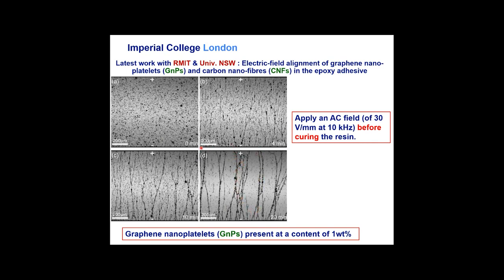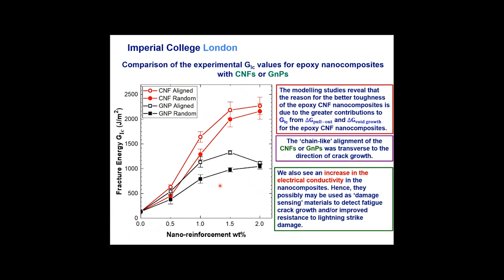And bear in mind, of course, there's one CFRP substrate there, another one there, and the crack will try to travel down through the adhesive. And therefore, these chains of GNPs actually help increase the toughness even further. Now, to show this, here's the results. Here's the fracture energy against the toughness of the joint we're looking at. This is the amount of GNPs or carbon nanofibers.